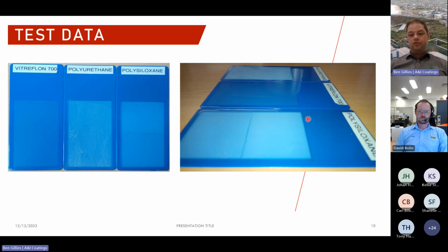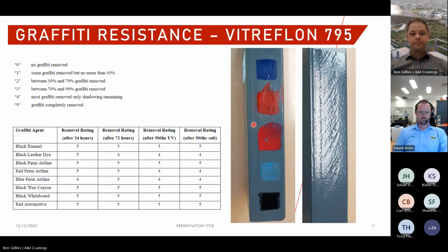These are the actual samples that we pulled out of the machine. So you can see the fluoropolymer is still fairly glossy. It has changed a little bit in colour to a minor extent, but it is still glossy, which means the coating is intact and still protecting the substrate. Whereas when it starts to get chalky, that's when you start to get film erosion.